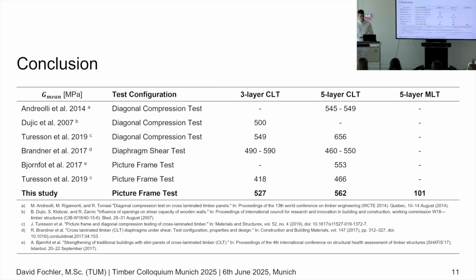This brings me to the conclusion. Based on these results, the conclusion I take is that the test setup we investigated was successful. The failures, the stiffnesses, and the shear moduluses we achieved for the CLT seem plausible, especially when compared with values from the literature. Here I have listed some of them. The 527 and the 562 fit quite well to the rest of the different types of testing methods.